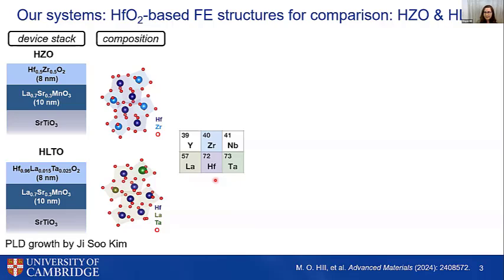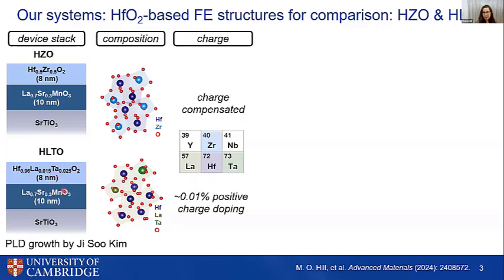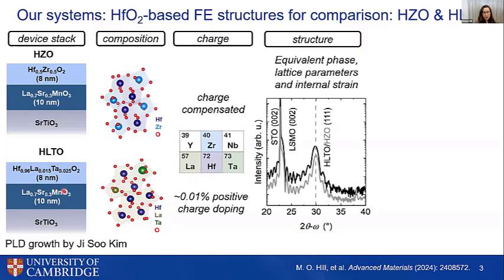But using PLD means we don't have 100% control. So in the end, we ended up with a bit of excess tantalum dopants, meaning we have a slightly positive charge doping. So there's a slight difference in the charge within these films. However, the structure of these films is really similar. They have equivalent phase, lattice parameter, and nearly equivalent internal strain.